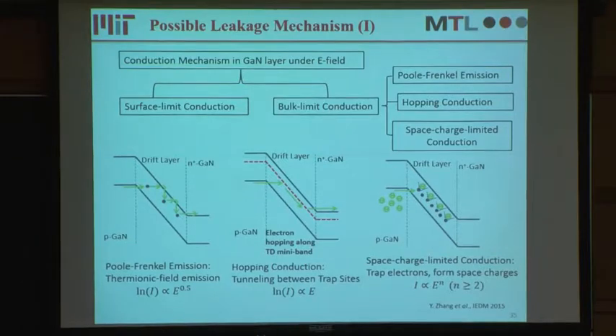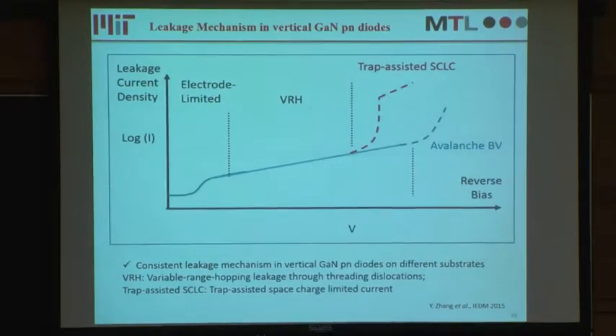As can be seen here, for these different leakage mechanisms, they have different relationships between the leakage current and the electric field. So we utilize these different relationships, and we also fabricated gallium nitride vertical PN diodes on different substrates - silicon, sapphire, and gallium nitride substrates. We also collaborated with Synopsys, the company, to build a lot of simulation models. After all this work, we're able to identify the leakage mechanism in the vertical gallium nitride PN diodes.